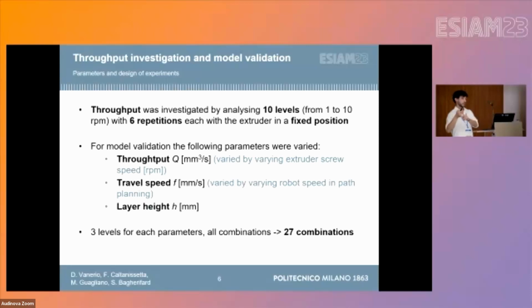Then, for the model validation, we have some parameters which we varied with 3 levels. These parameters are the volumetric throughput, the travel speed as defined before, and the layer height. We made all the possible combinations, reaching 27 different combinations. For each combination, we performed 10 different measurements, so we reach a total of 270 measurements.